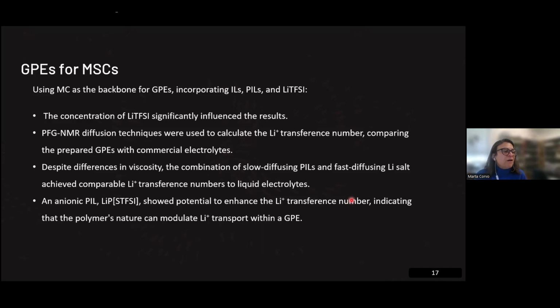What we have found is that we could obtain the lithium transference numbers from the diffusion NMR and compare them to the commercial electrolytes. Despite the differences in viscosity, we could manipulate the transport properties and the diffusion behavior by changing the matrix and the matrix core, either being more neutral or more anionic in this case, towards promoting the dissociation of lithium and a fast diffusing salt. So we could approach the transference numbers of the liquid electrolytes. This anionic polymer that we have made also promoted lithium transference numbers quite well.